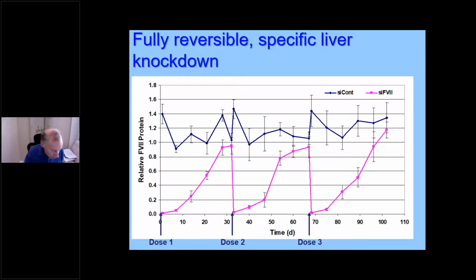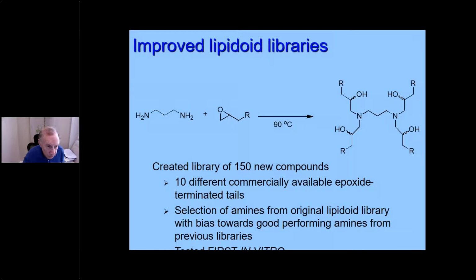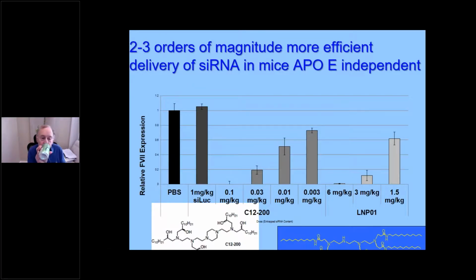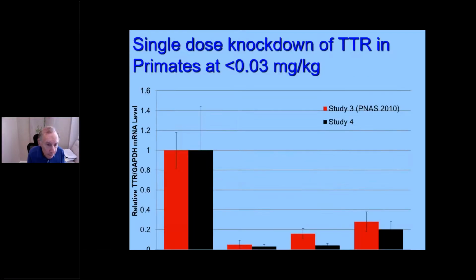So here what we did is we took some of our leads, and if we go to the next slide, we now used an epoxide chemistry to make 150 new compounds. And again, we selected the amines from our original library. We tested these in vitro, and what we find is the best ones, next slide, are 2 to 3 orders of magnitude more efficient at delivery of siRNA in mice. You can see this, the C12-200, you see the structure, is 2 to 3 orders better than the LNP01. And if you go to in vivo experiments, you try to knock down transthyretin, next slide. You are able to do that even in primates.